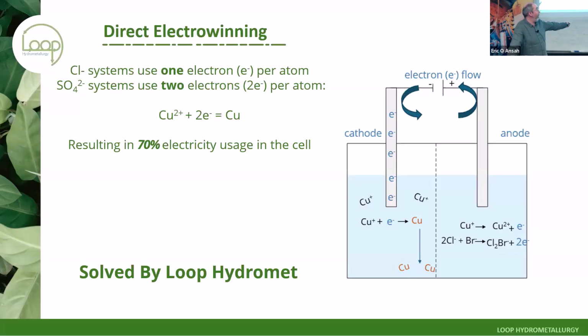The catholite then passes through a membrane into an anode chamber where the remaining copper is reoxidized, but critically, because we have the presence of both chloride and bromide, we actually form an aqueous species, Cl2Br-. This is a major advantage because any other chloride-based technology that's done electrowinning, and there have been ones in nickel and silver and things like this, they all produce hot, wet, corrosive chlorine gas in large volumes. It's a materials handling nightmare and a safety nightmare.